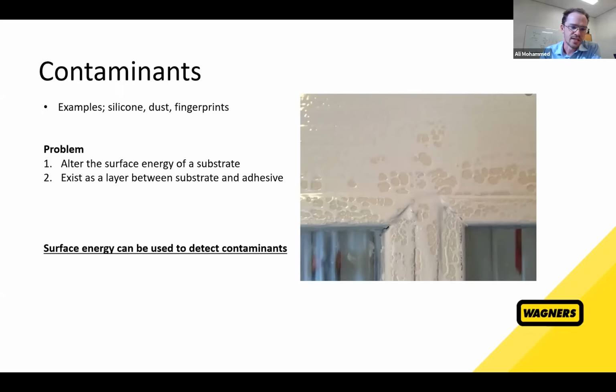If we dive down into what contaminants actually do, because they exist on the surface of a material, their surface energy affects the surface energy of the substrate. So whatever the contaminant is, that affects the surface energy of the substrate because it exists on the surface. And aside from that, the contaminants exist as a layer between the substrate and the adhesive. So even if you bond up a substrate with a contaminant and get a very good bond to the contaminant layer, the bond between the contaminant and the substrate could still be weak, and you get a poor bond no matter what you do. So ideally, before you do a bonding operation, you remove all contaminants and ensure that everything is very, very clean to eliminate the risk of this sort of stuff happening.